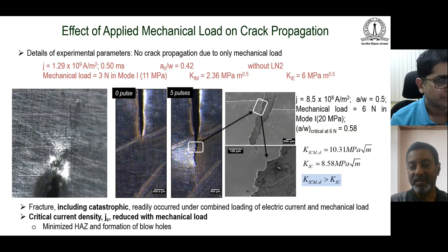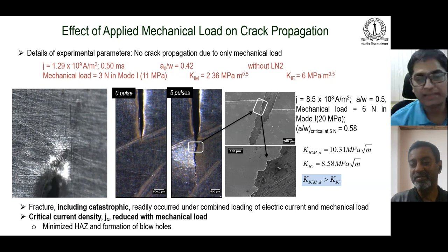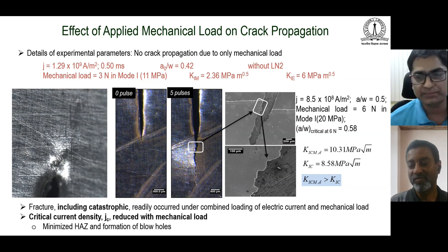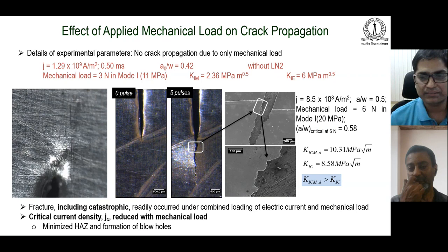The other question from Satyam is, what is the driving force for dynamic recrystallization observed in the healed crack? Because there is a lot of plastic strain that is being generated there, and that's what we think is responsible for the recrystallization. Remember that this is sitting at high temperature, but at the same time there are large compressive stresses being generated there. So that's what we think now.